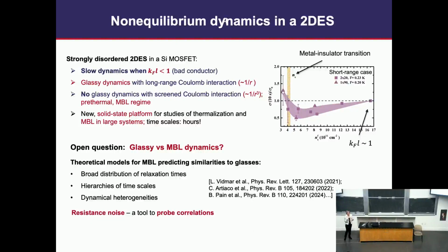And now, having this system, we can address other open questions that are currently of interest, in particular the more detailed differences between glasses and MBL. For example, there are some theoretical models that predict some similarities to glasses, such as a broad distribution of relaxation time, some kind of hierarchy of time scales, and dynamical heterogeneities. So to address these finer points, you want to really probe the correlations, the evolution of correlations in the system.